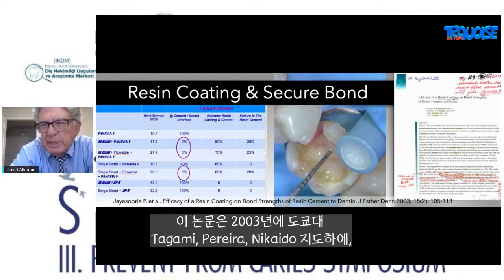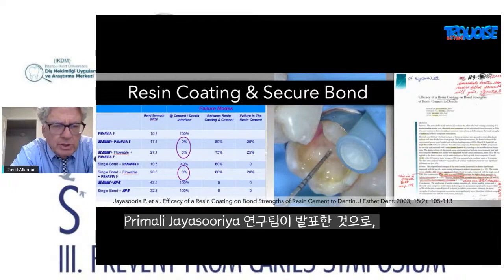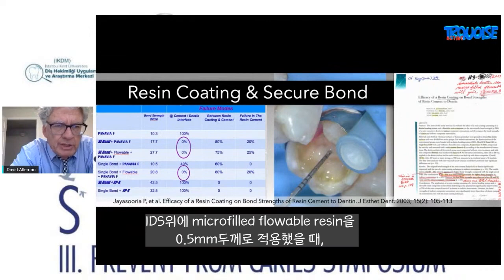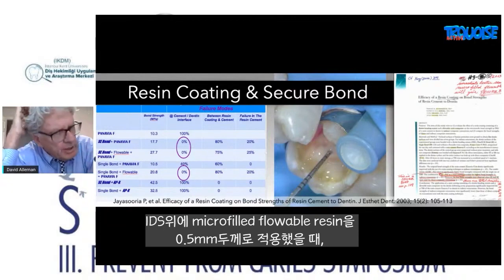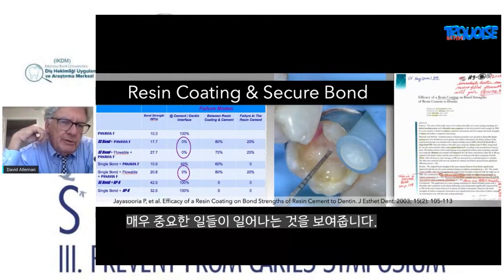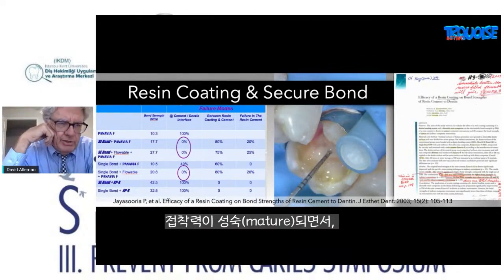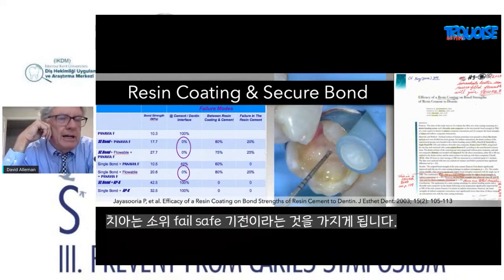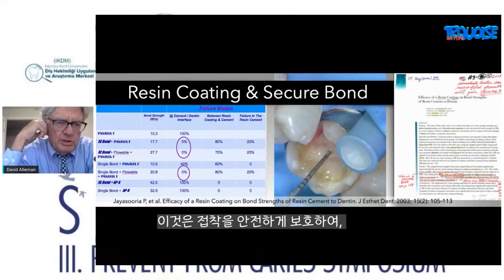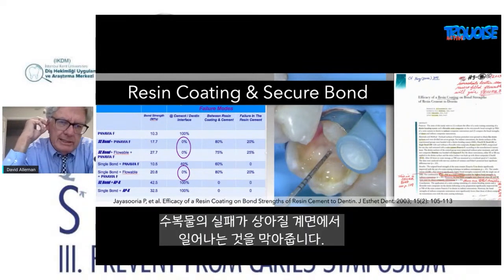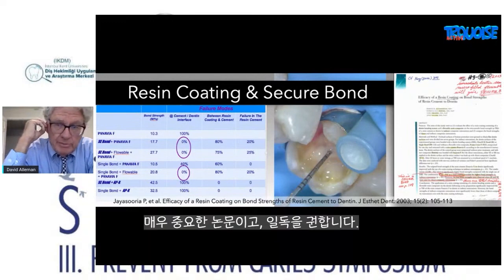And so this paper published in 2003 by the team out of TMDU, under Pramali Jayasuriya's work under Tagami, Pereira, and Nikaido, showed that if you put a 0.5 millimeter of a microfilled flowable on top of your immediate dentin sealing, then several very important things happen. The bond strength matures, and it allows the tooth to now have what's called a fail-safe mechanism. And it secures the bond so that if the restoration were to fail, the failure would not come at the dentin interface.